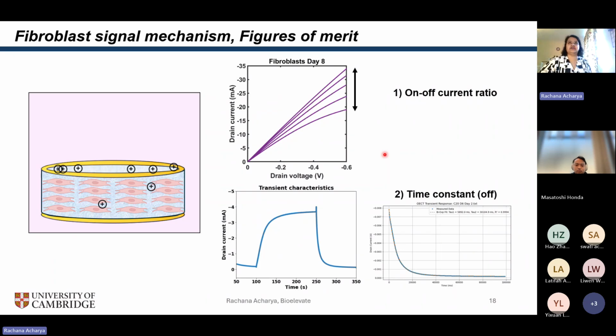If I want to have a numerical value on this, what can I consider as my figure of merit? We're going to extract two different parameters. The first is from the output characteristics, the on-off current ratio, which is the ratio of the current in the on curve, the highest current in the device, to the current in the off state of the device. The reason I'm doing that is because the off current as a ratio to the on current is what is changing as my fibroblasts are growing. I'm going to measure it for every device individually, because otherwise, if I have varying on currents in my device, it's not a fair comparison to compare the off currents to one particular one. So that's my first figure of merit: the on-off current ratio as a function of time.